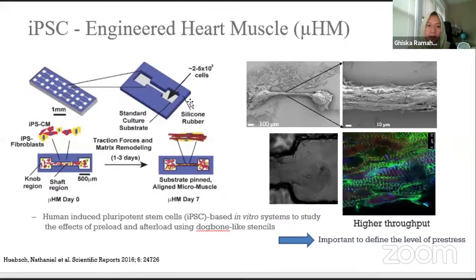You have the mold and you can pour your cells into this mold, and by several days you can see incorporation of the cells inside these stencils, and it can do traction force and matrix remodeling between the cells, and you can see these highly aligned cells within this area. You can see from the electron micrograph picture, this is the cells. And here in the middle of the tissue, we can see highly aligned cells, which is called sarcomere.